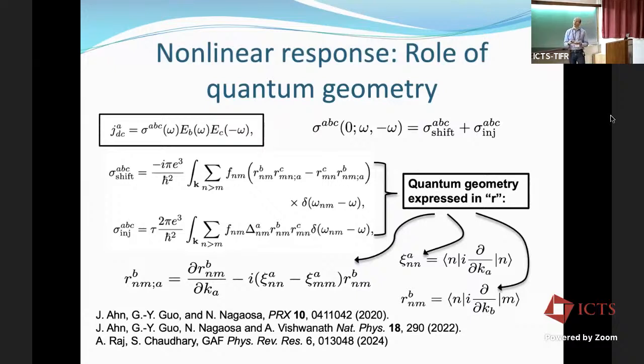So we looked at this question from the point of view of a simple perspective. So we asked, how much of that quantization is restricted to that low energy model? So basically, we wanted to look at a comparison between effective low energy theories of nonlinear responses and more complete band theories that have a full band structure, and ask what the differences were. So first, how is the quantum geometry present in the response? So this is the DC response. We have frequencies at two different values that are equal and opposite, and this produces a DC response, which is the sum of these shift and injection currents that I mentioned. These shift and injection currents are integrals over k-space and Fermi occupation factors, and there are these little r's here.